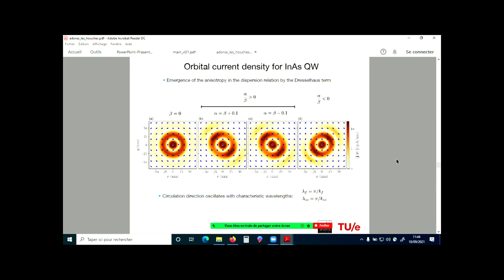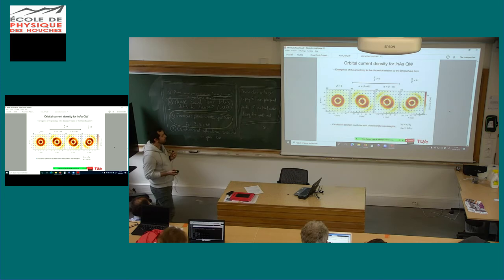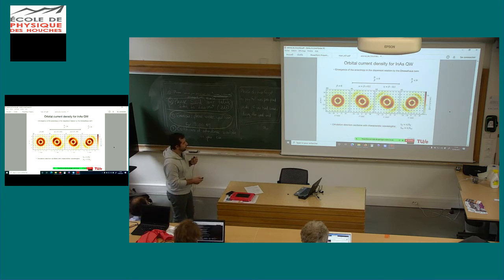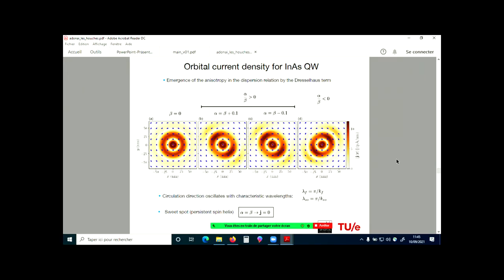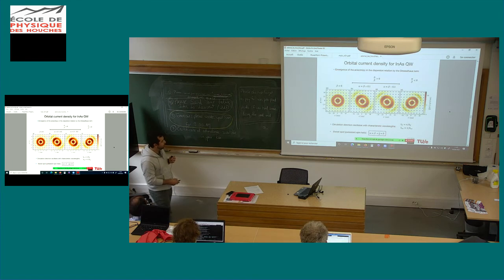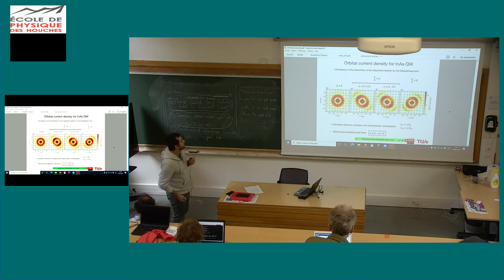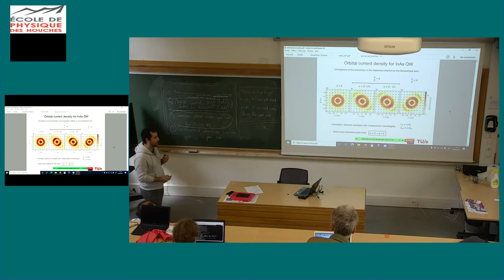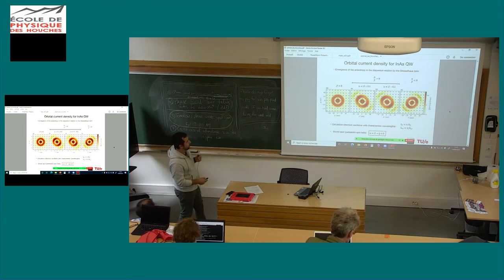As I mentioned before, alpha is dependent on the external field, so it's controllable by electric field. And we can basically tune this alpha to be negative with respect to beta, and this will give rise to a density of current along the opposite direction, rotated 90 degrees. But I think the most interesting thing here is that when alpha equals beta, we call it the sweet spot here, for the spin magnetization we have what's called the persistent spin helix. But in the case of the orbital contributions, this is 0. So the current is 0 for alpha equals beta, and for symmetric values around alpha equals beta, we have an inversion of circulation. As you can see, here are two plots.